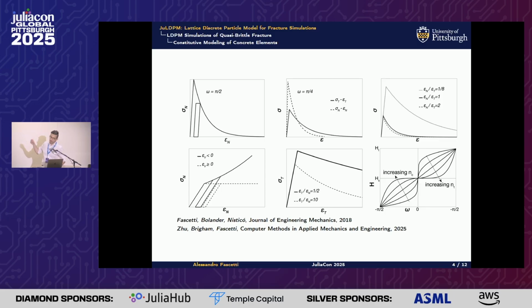As I said before, we use vectorial constitutive models, which means that the model generation is relatively more tame than when you have to describe fracture in a tensorial framework, because now you can enforce exact fracture energy release rates for mixed mode fracture, which means when you have mode 1, which is tension, and mode 2, which is shear fracture, then things become really complicated in a 3D sense, but at the 1D level of each of the lattice elements, you can really enforce very complex fracture models.